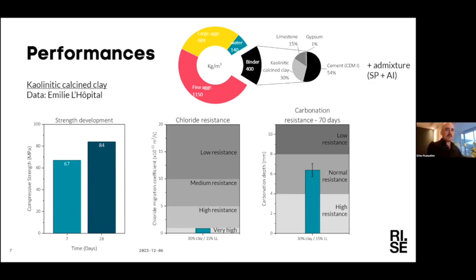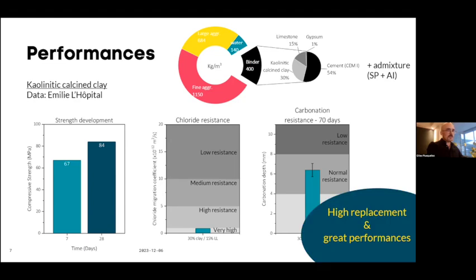So with this kind of material, we can have high replacement of cement, and this is still linked to great performances. And now we will still have to do this work for illitic clays, so after, for example, flash calcination. And of course, this is also linked to a really big decrease of CO2 emissions of, let's say, about 40%. Yes, so that was for the clay.